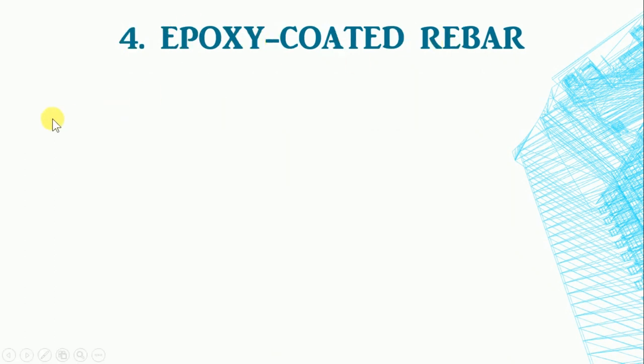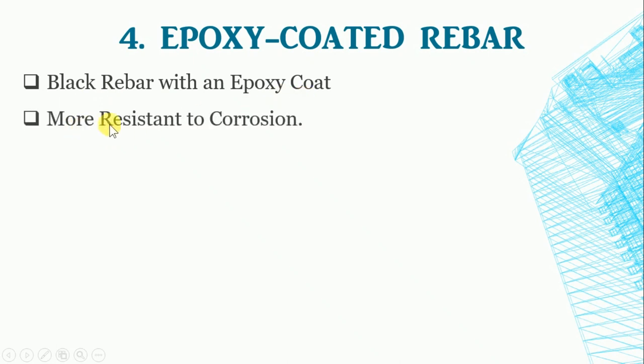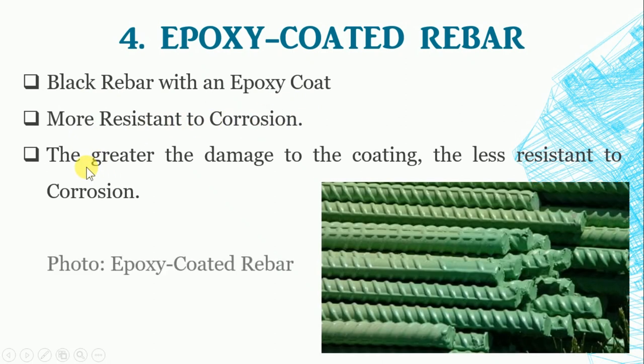Epoxy Coated Rebar: Epoxy coated rebar is a black rebar with an epoxy coat. It has the same tensile strength but 70 to 1700 times more resistance to corrosion. However, the epoxy coating is incredibly delicate — the greater the damage to the coating, the less resistance to corrosion.